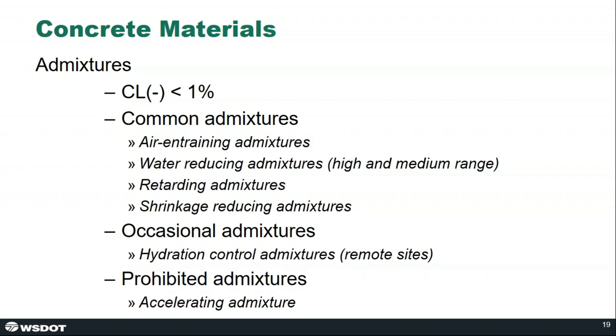And we do prohibit some certain admixtures, mainly accelerating admixtures. Historically, accelerating admixtures had chlorides in them, which was not desirable from a corrosion standpoint. There's a number of modern accelerating admixtures out there that are chloride-free, but we still prohibit those for the same reasons we prohibit type 3 cement, due to a concern over heat of hydration and thermal cracking.